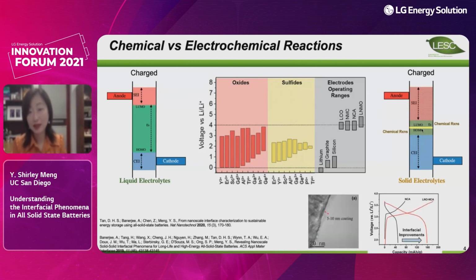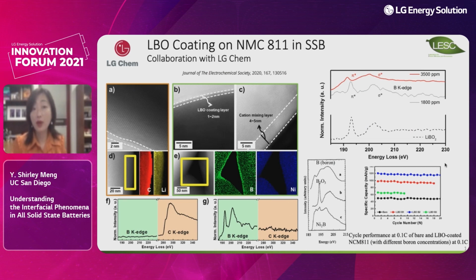However, thanks to our industrial partner, colleagues I would say, Toyota, who released the coating of lithium niobate oxide, that gives us some hope that barrier layers like lithium niobate oxide can stop the chemical reactions at the solid state electrolyte interface, potentially enabling the utilization of sulfide electrolyte with NMC-based cathode. In the last few years, we were glad to collaborate with this company, the logo should be changed to Energy Solution, but pardon me for still using the old logo.